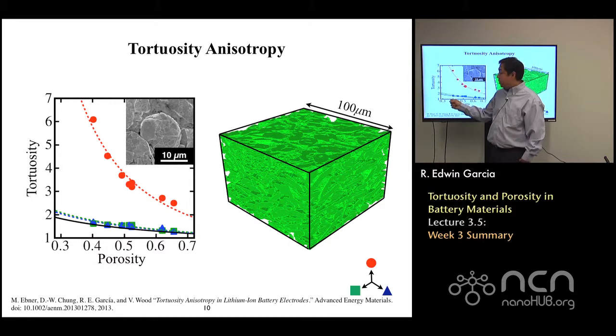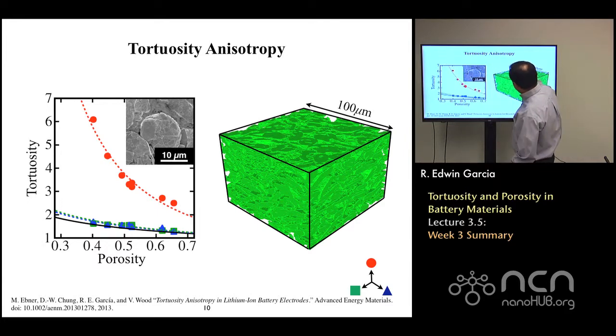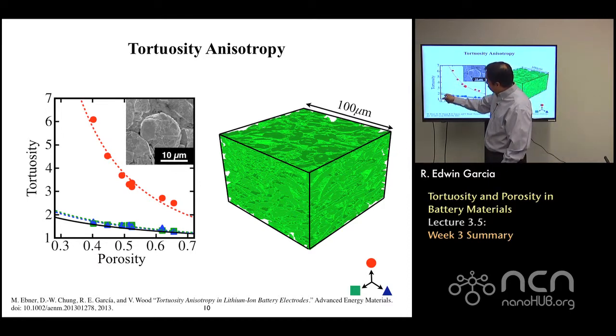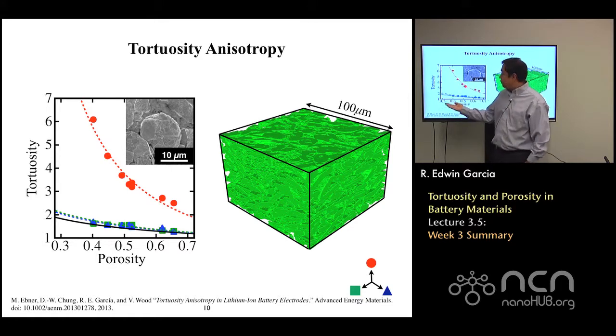As you come down to very low values of porosity, you can go from a tortuosity of 1.5 to say 3 times that number or more, which in this case becomes a value of 6. In this case you should be able to pack more particles as this aspect ratio allows for less interstices to be left behind, but the perfectly spherical particles will always stay down here. So there are some benefits and drawbacks.